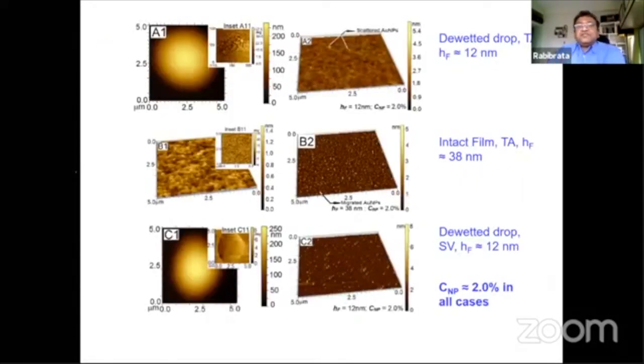However, the most important slide is probably this one, again, where we did some very careful atomic force microscopy, actually to see what happens to the nanoparticles. Because here, please do remember, we could not do an X-ray scattering because the film was dewetting, and you don't have a continuous film. So because of the correlated roughness you have, you will not get some fringes, right?